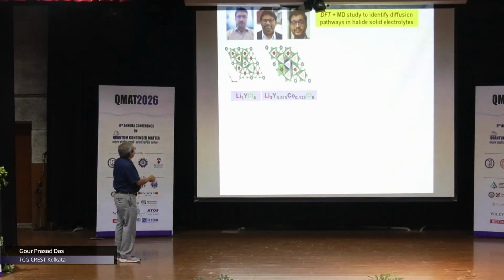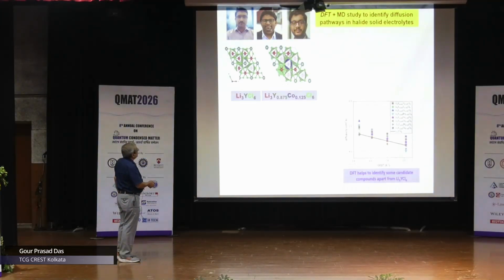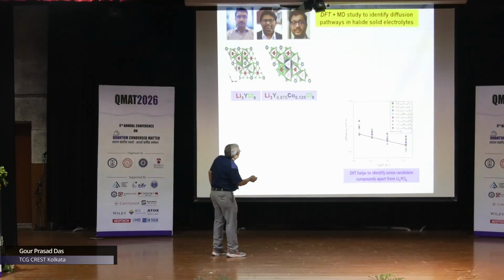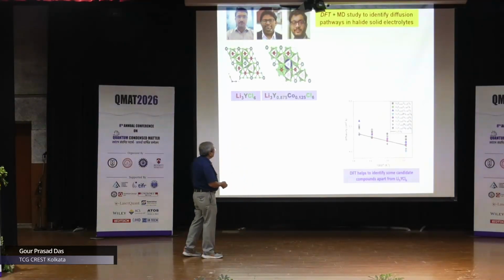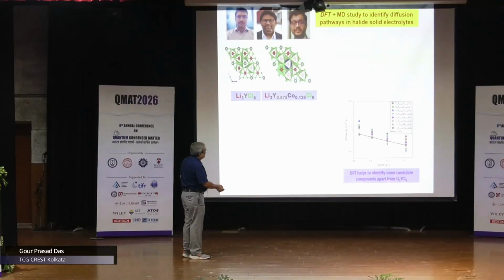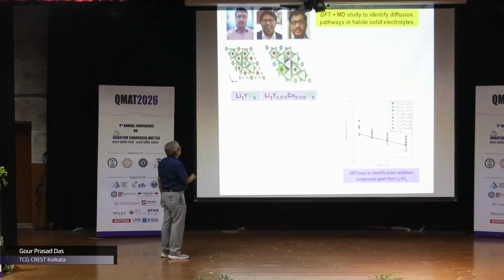advantages and limitations. So Tanmoy has done a lot of work on this Li3YCl6, where we are basically interested in optimizing the ionic conductivity of lithium. So yttrium is alloyed with different transition metals in the 3d series, and that's what has been done. You see here, yttrium is alloyed with titanium, vanadium, chromium, manganese, and so on, up to copper, everything. And it shows the diffusivity as a function of inverse temperature. You can see that. And indeed, DFT helps us to identify some of the candidate compounds apart from the pristine parent Li3YCl6.